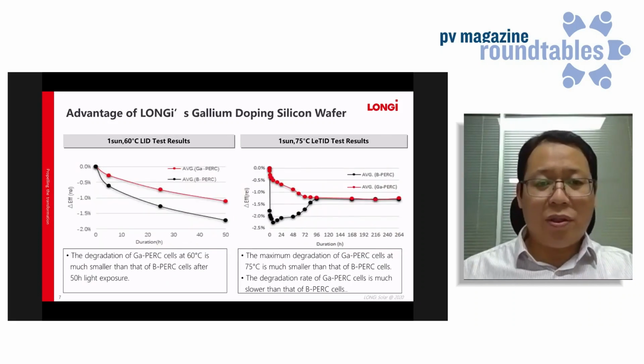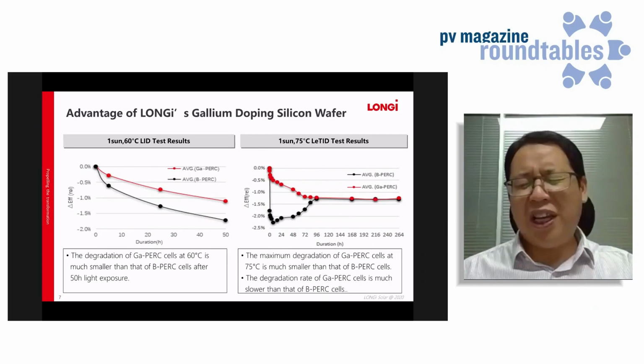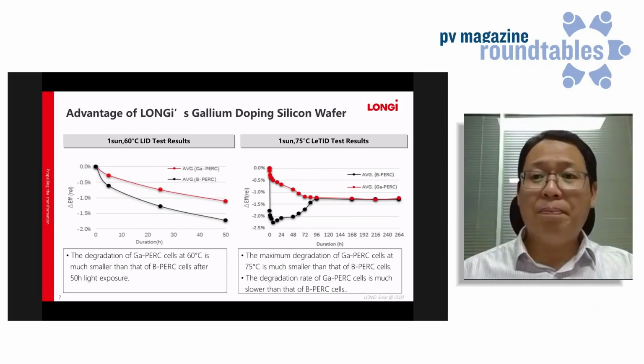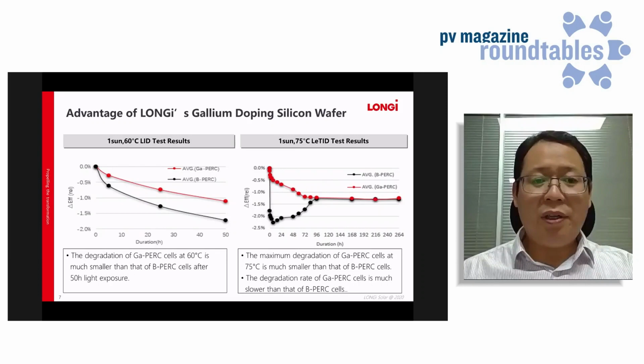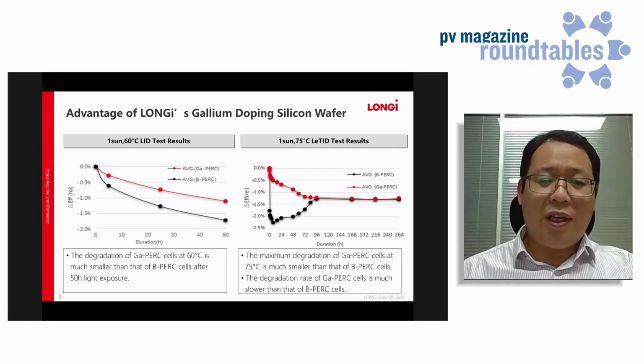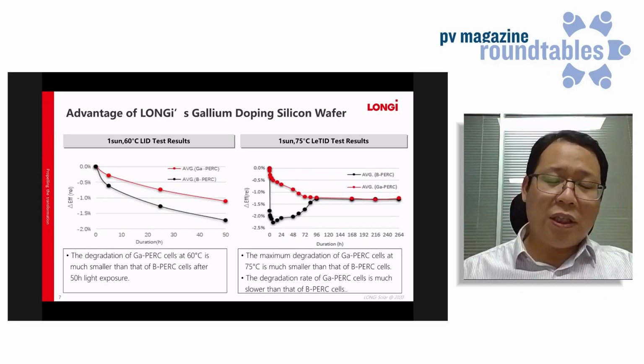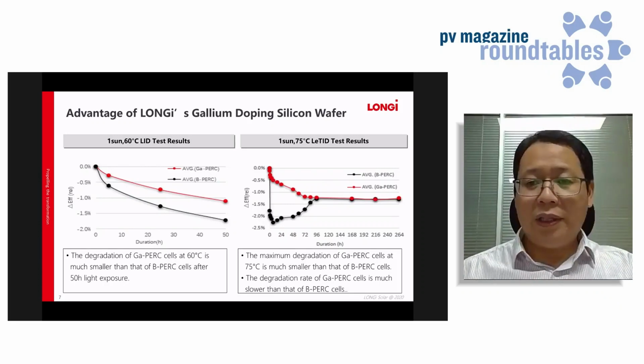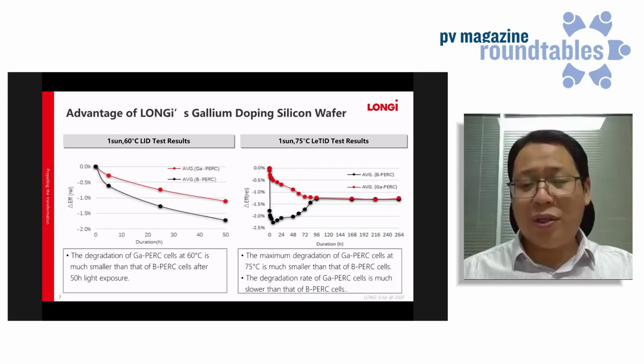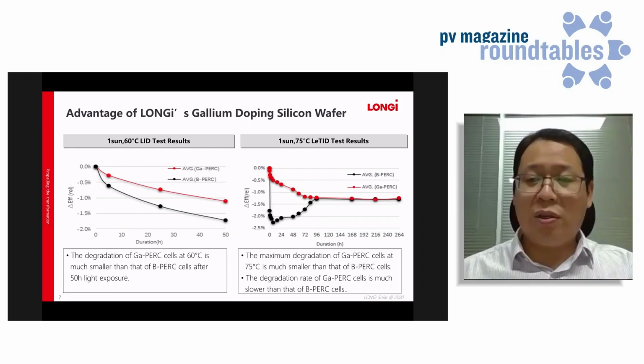So this picture also shows LETID results from the cell manufacturer. You can see that at 60 centigrade, the degradation of the gallium doped wafer is lower. Also at a very high temperature, 75 centigrade, the degradation rate is lower and the degradation is lower.